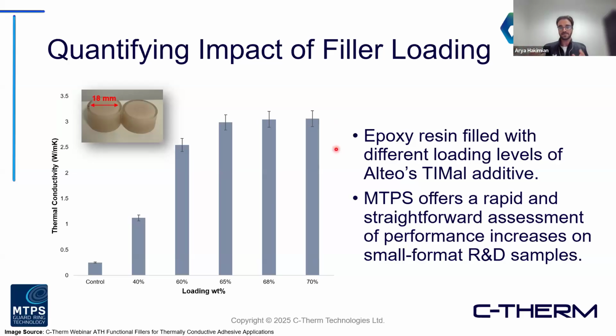But in a scenario like this, where you're looking to quickly quantify, especially in an R&D scenario where you're maybe going through various formulation iterations, one of the quickest and easiest ways to go about this is with the MTPS. In this testing, the MTPS was the method of choice for a variety of reasons. One being that the samples were quite small, about 18 millimeters in diameter. This is essentially the minimum size for MTPS testing.